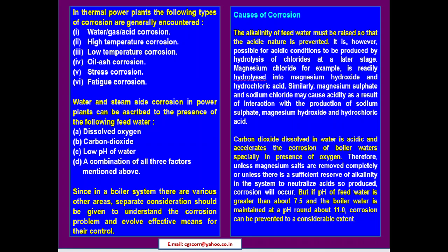Water and steam side corrosion in power plants can be ascribed to the presence of the following in feed water: 1. Dissolved oxygen, 2. Carbon dioxide, 3. Low pH of water, and 4. A combination of all the three factors mentioned above. Since in a boiler system there are various other areas, separate consideration should be given to understand the corrosion problem and evolve effective means for their control.